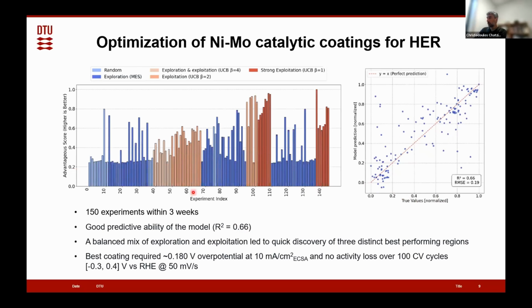The color that you see here indicates whether the model was employing a more exploratory approach or exploiting the already collected data. And we employed a mix of exploration and exploitation of the results in order to identify the optimum in this synthetic phase space. And by doing so, within 150 experiments, we managed to get very active coatings that required less than 180 millivolts overpotential at 10 milliamp per square centimeter surface area normalized activity. That showed no activity loss over these 100 CV cycles.